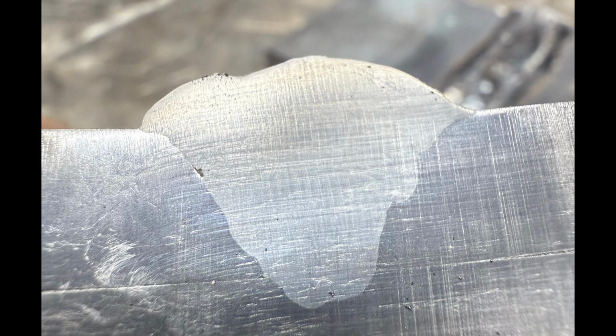The biggest problem with what we see here is that this is going to be a common occurrence, and you as a welder will never know that this is there unless you're doing some kind of x-ray or ultrasound or something, which obviously you're not doing. So if you go and repair 3/8 plate with a backing strip, it's entirely possible that the weld will fail under stress because you have stuff like this inside of it. Not to mention, you might do a test weld on perfectly clean material and then go and do this on something that's less than perfect and have a completely different result.